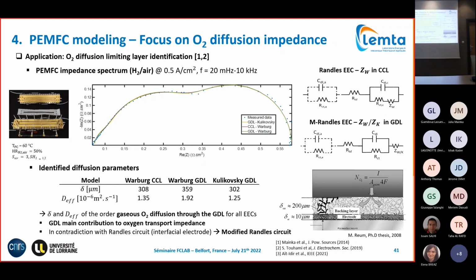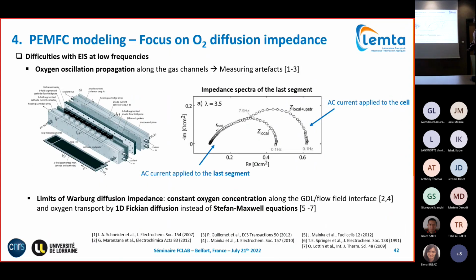So the conclusion is that the diffusion impedance of our spectra is more probably linked to the GDL rather than to the electrodes. And in this case, this configuration, putting the oxygen diffusion impedance outside the cathode reaction circuit, would be more reasonable. This was our conclusion, published as well. And with this, I will stop on the low frequency interpretation causes.